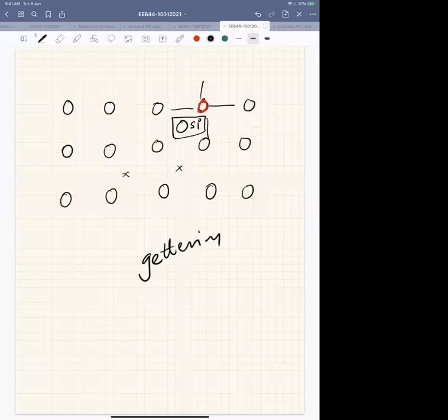That's the reason, right? As I told you, when you implant, you bombard your silicon crystal with arsenic ions at very high energy, right? So arsenic is implanted, but the crystal structure is destroyed because the high energy ions are bombarding it. It removes the silicon from its lattice sites, so that means we have an amorphous kind of region, with no order, nothing, right?